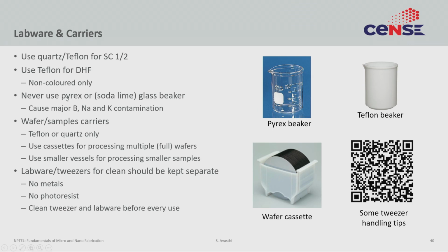Try to avoid Pyrex or soda lime beakers. They are very cheap, very easily available, but if you look at it chemically, soda lime glass or Pyrex glass is full of boron, sodium and potassium, and that will cause that type of contamination on top of your wafer. So please avoid those. Try to use quartz beakers. They are available, a little more expensive. The wafer and sample carriers must also be Teflon or quartz only.